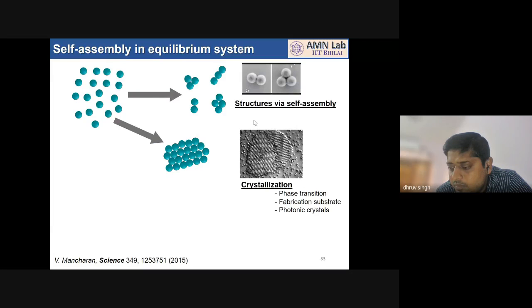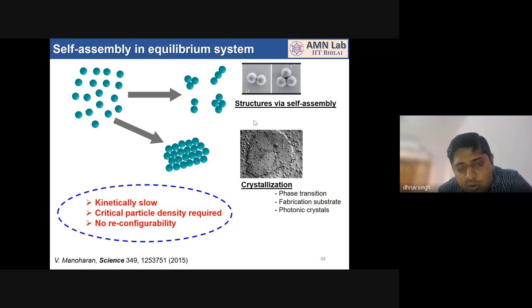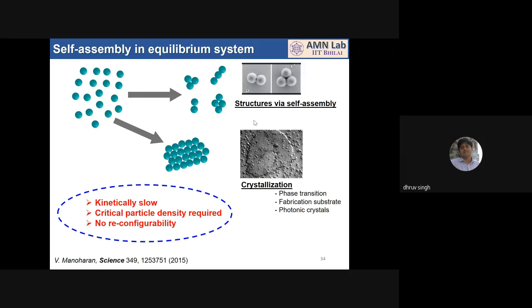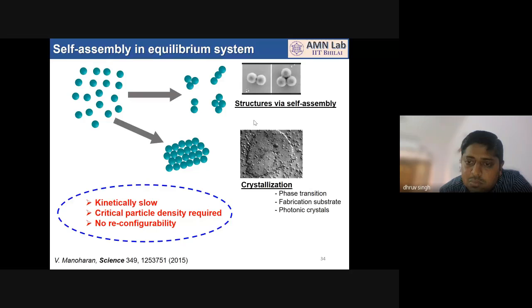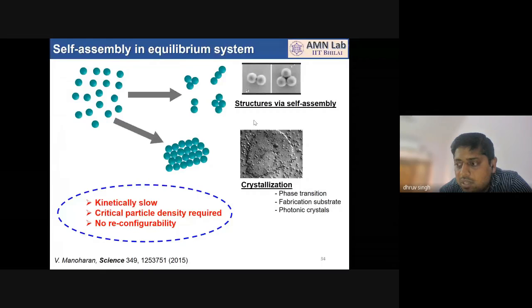The whole branch of physics that's called colloidal physics works on these things. But the problem is that this type of assembly or crystal or structure formation in colloids suffers from some very basic problems. Like, it's a kinetically slow process. It may take from a few hours to several days to see some structure formation in the colloidal system. It needs some critical particle density. For example, if you want to form a colloidal crystal, then you must have at least 50% particle fraction, particle density. Otherwise, nothing will happen in the system.